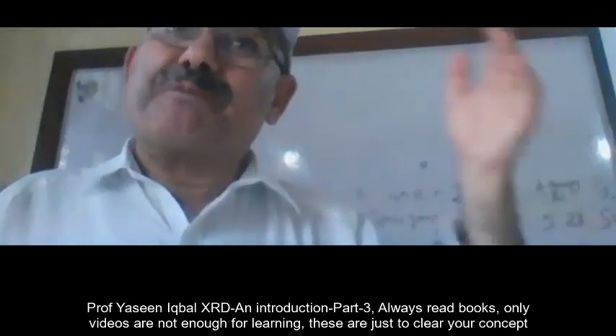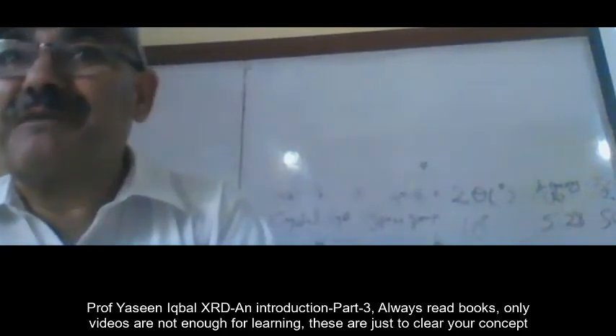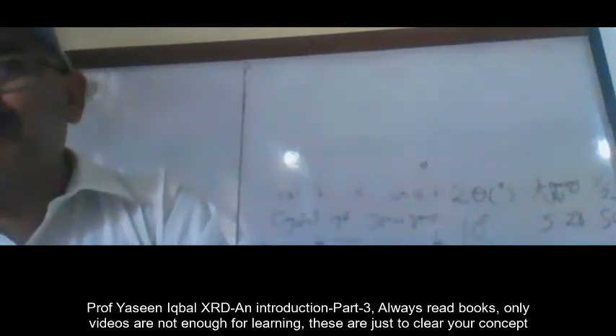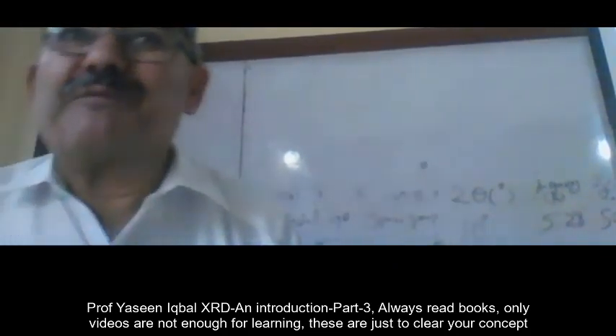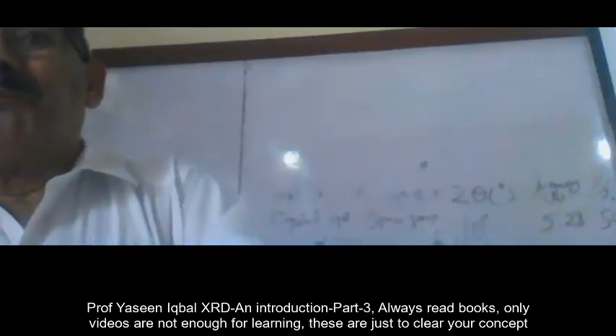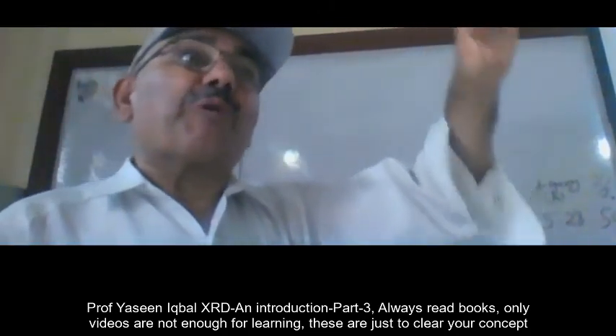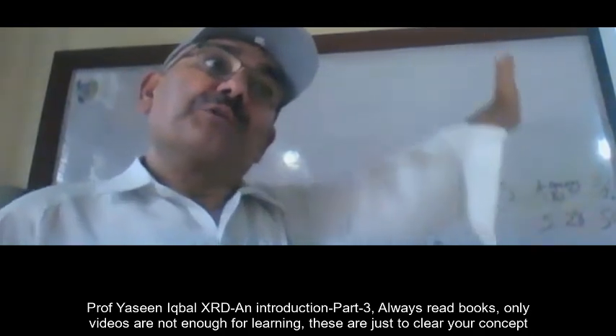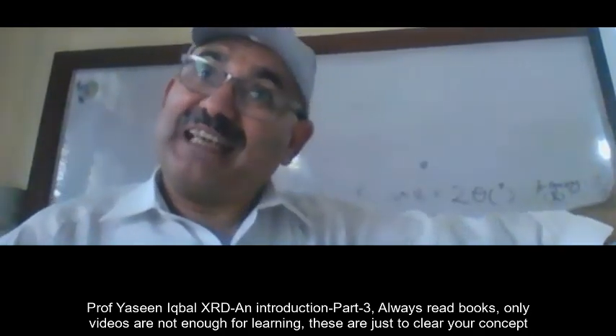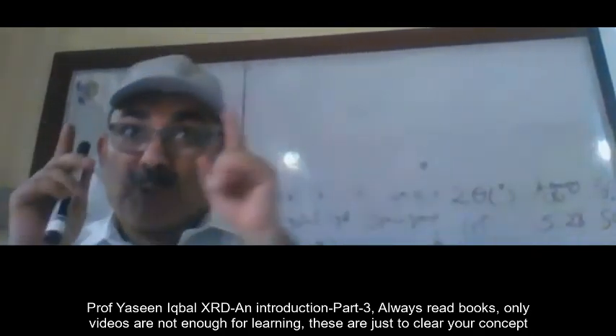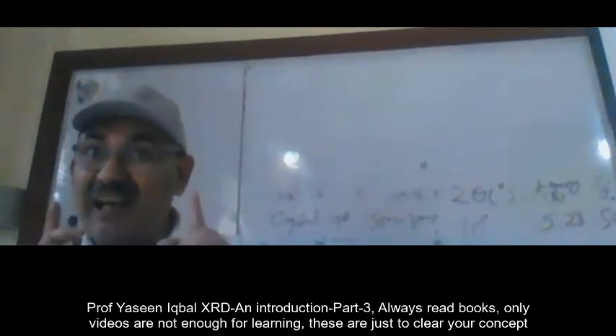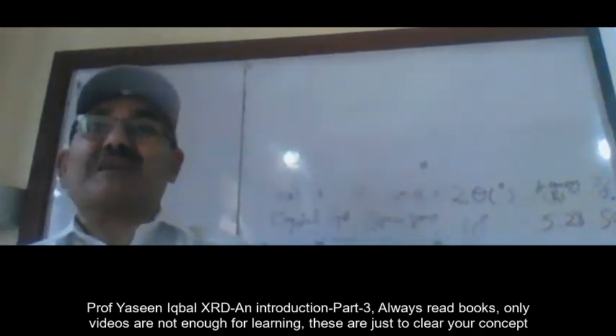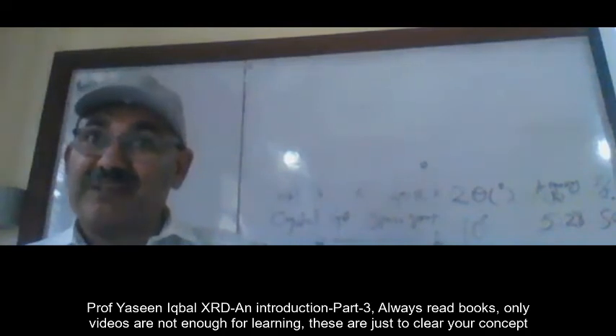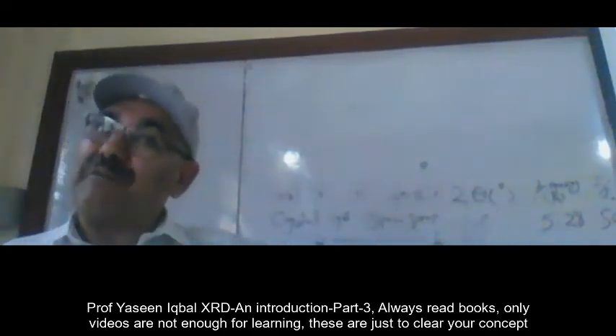And the 50 can be 55, it can be 45, it can be 52 or 53, but it will be proportional to the intensity of the standard data. If that proportionality is lost, this means there is some problem either in your experiment or the phase is not that phase.